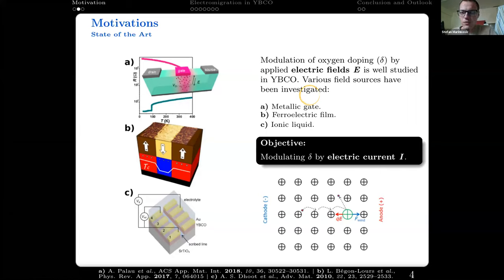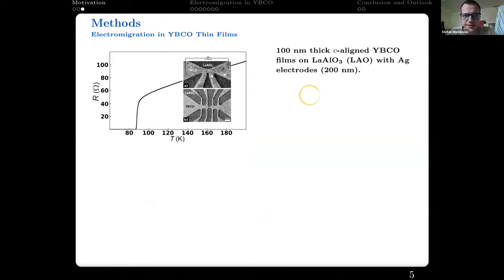Because in YBCO we have significantly larger diffusion of the oxygen ions, we can expect that electromigration in this material will be selective to this oxygen, and by that will modulate all the other properties of the material. To do this, we used two different samples, both 100 nanometer thick c-axis-oriented YBCO films on lanthanum aluminate, and all of them behaved as very good superconductors. We got them from Anna's group, with clear transitions thinner than 1 Kelvin at about 90 Kelvin.